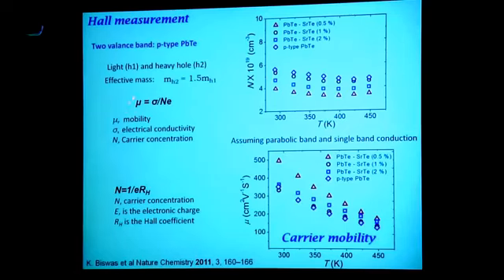From the carrier concentration and the conductivity, you can get the mobility, and so here's the mobility for the three samples that have the same carrier concentration. One is pure, one has 2% strontium telluride, and one has 1%. And they have the same mobility. So in other words, this system doesn't know strontium telluride is there. It acts as if it's pure. This was surprising because in general, our experience is when you put something in lead telluride or in any semiconductor, mobility gets degraded because you get scattering off of the lattice sites. But here, we pay no penalty in mobility. And that's a very good sign, and I'll come back to that because this is critical.